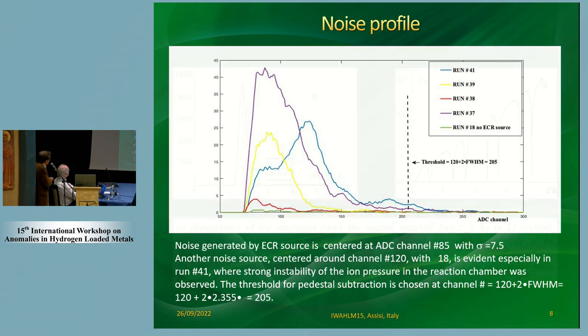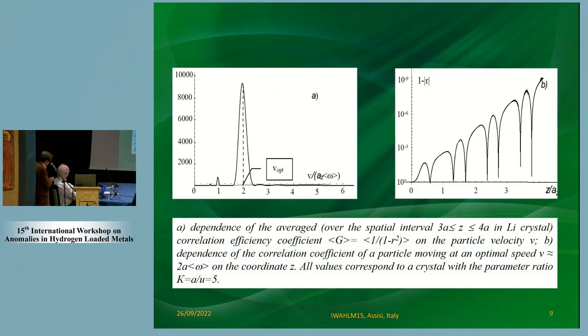Well, let's go ahead. This is an example of the dependence of the factor G, which is this value here, on the frequency, in the sense of the energy. This is the ratio between the velocity of the particle and the path which the particle has inside the lattice. You see, there is a peak at twice the frequency of the longitudinal lattice. And this is exactly what the parametric resonator model predicts.